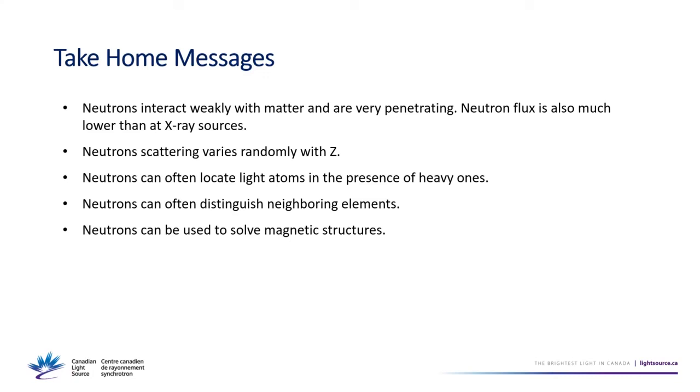Besides diffraction, if you're doing just regular powder diffraction, a reactor source is usually sufficient. If you're doing pair distribution function, you're going to need a spallation source because you need that epithermal tail to get to high enough Q values. So usually a reactor source does not give you a high enough Q value to do PDF with.